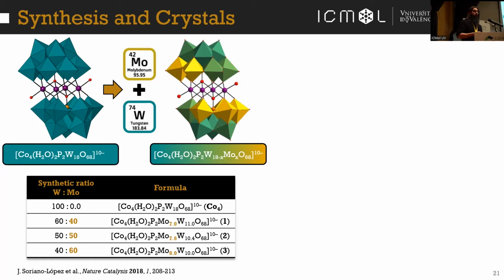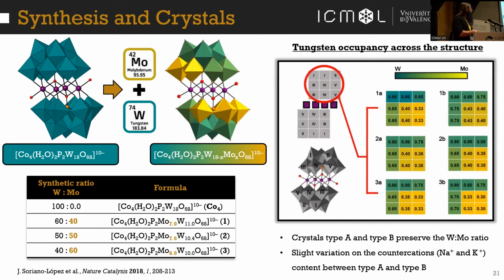And also from each synthesis, we got 2 different polymorphs, and so we end up with 6 different crystals, and we studied the structure of all of them. So here in this picture, I'm showing you the tungsten occupancy across the structure. So these squares here belong to these different positions of the addenda atoms. And as you can see here, the tungsten has some preferential sites in these positions.